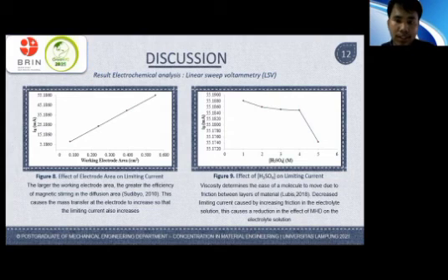But for the concentration of sulfuric acid, we see that the viscosity is increased, but the limiting current value decreases. We see that 3 molar is optimum, because sulfuric acid does make the leaching process faster. However, for the MHD process it is efficient at 3 molar because there is a significant decrease at 5 molar, and it wastes sulfuric acid.